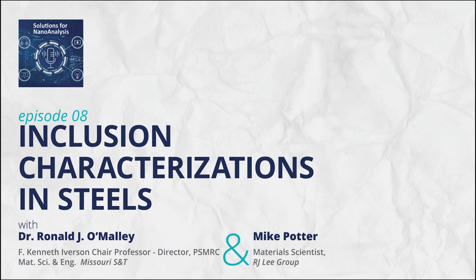And so over time, it shifted from looking at the large macro inclusions down to, right now, typically around 1 micron, which has become sort of the industry standard. A lot of that is based off of the SEM technology using standard tungsten source electron microscopy. The minimum size you can really get with some decent resolution is probably down to 1 micron. Doing it in such analytical conditions that analysis is done within an hour or two as opposed to days.